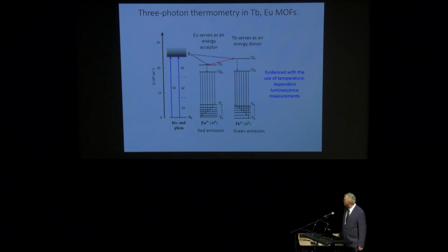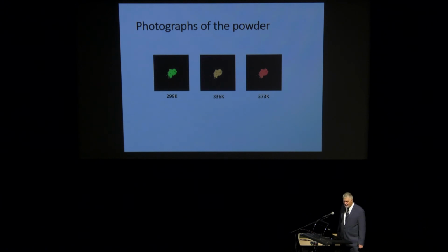The mechanism is as follows. We have ligands, which are organic, which are, let's say, nonlinear optics active. We can excite them with one photon in the UV or three photons in the near infrared. Then there's energy transfer, so they act as antennas. There's energy transfer to the lanthanides, and then there's energy transfer between the lanthanides. And in the end, we have these several luminescence bands that we can follow. And as you can see, the result is really very well visible.